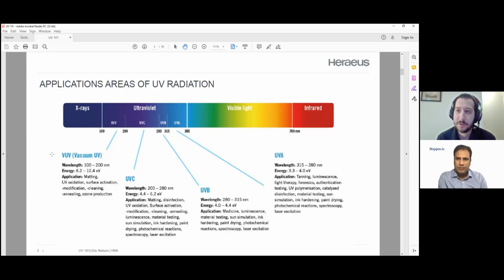You could achieve this also through a different route, which is the direct polymerization reaction, which is what UV curing is all about. So instead of waiting for a solvent to evaporate off and dry, you have an instant chemical reaction that cross-links the material and causes a hardened cure.